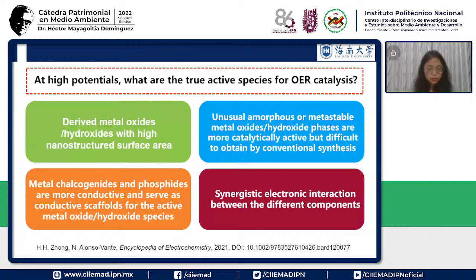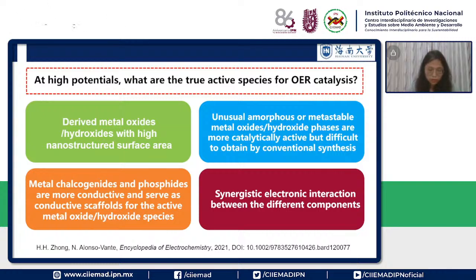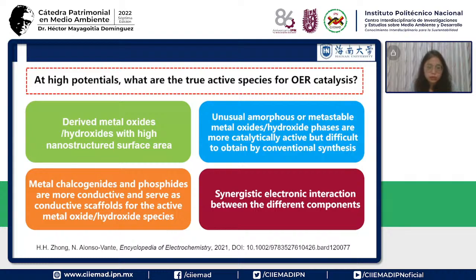And the third proposal is that metal chalcogenides are more conductive and can serve as conductive scaffolds for the active metal oxide and hydroxide species. That means there is a connection between the chalcogenides and the active metal oxide or hydroxide. Yes, we are sure the metal oxide or hydroxide is more active for the OER, but the metal chalcogenides also play an important role in conductivity, because we know the oxide or the LDH or the hydroxide are not so conductive for the electrochemical process.